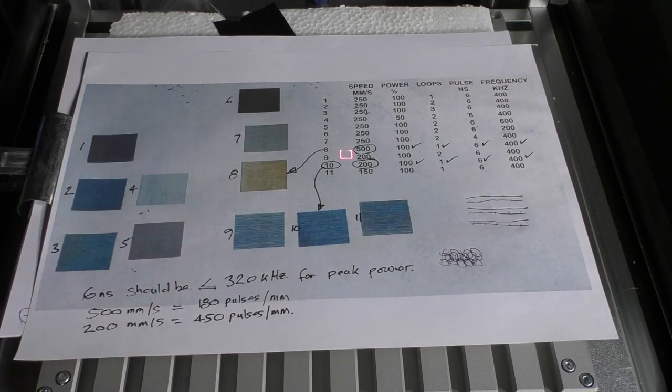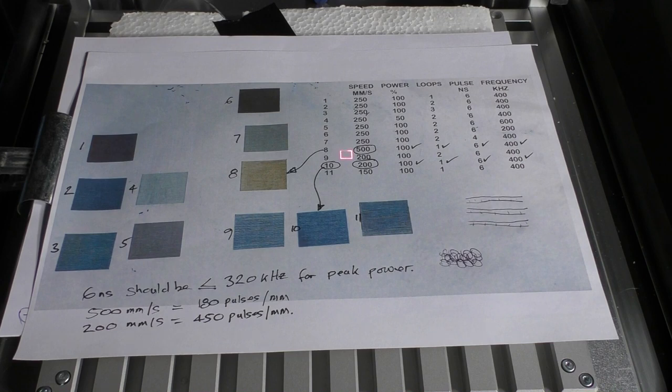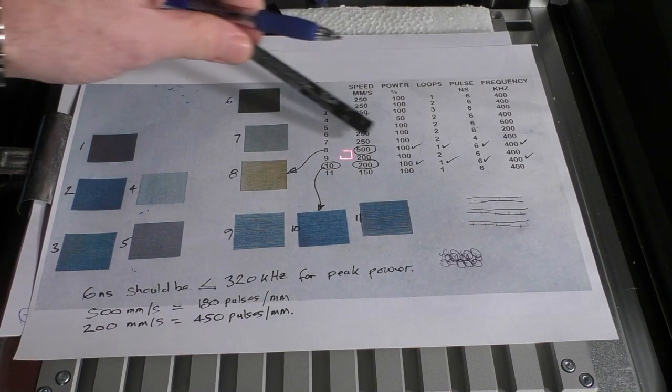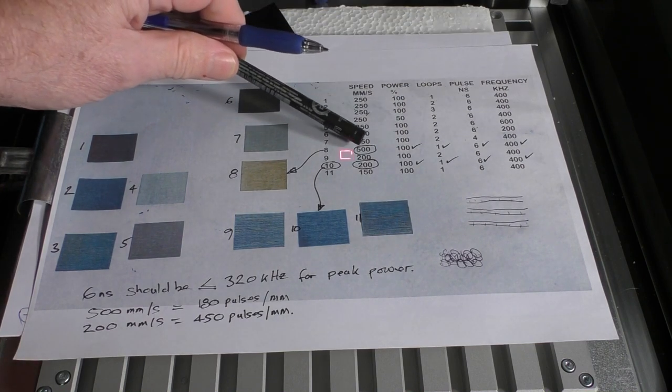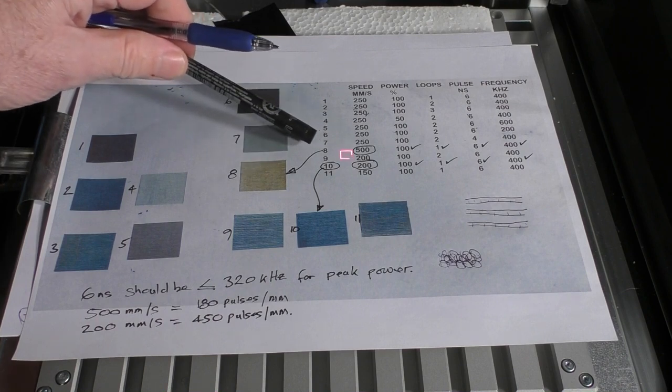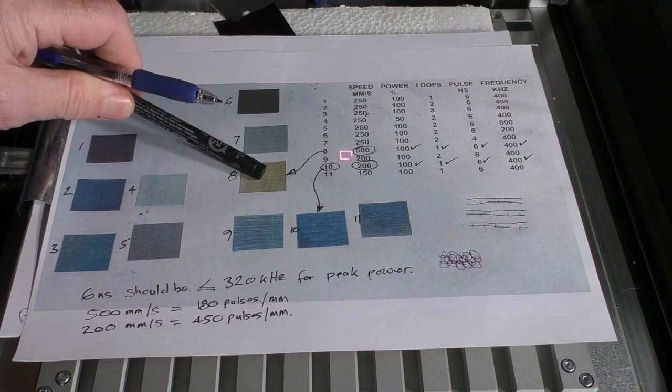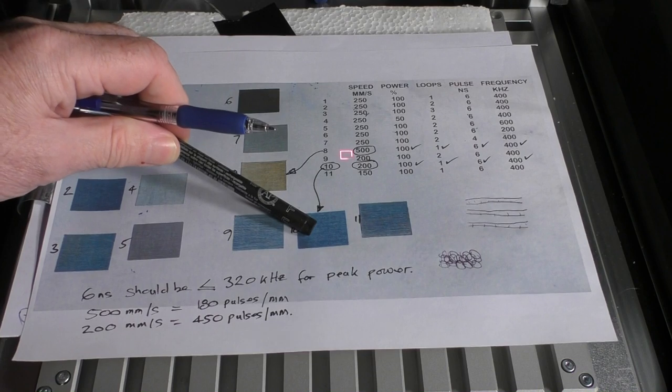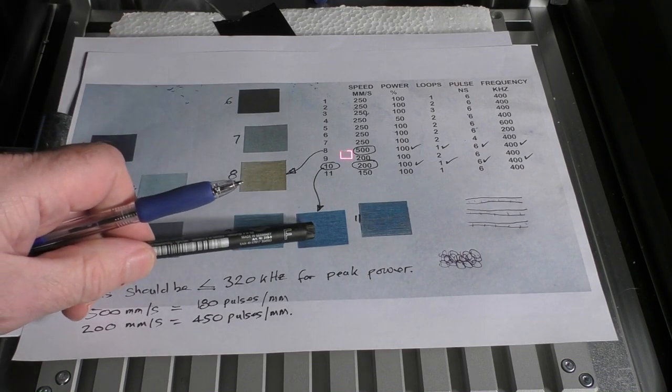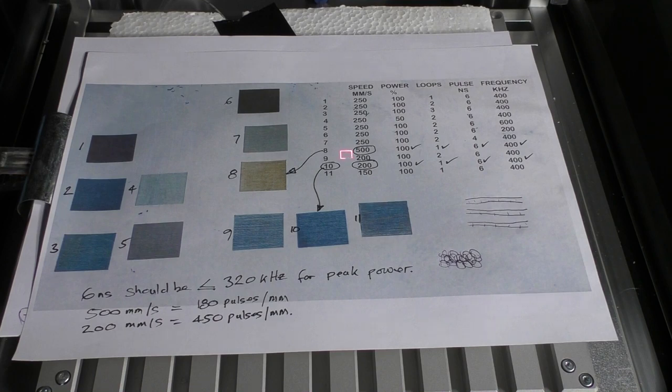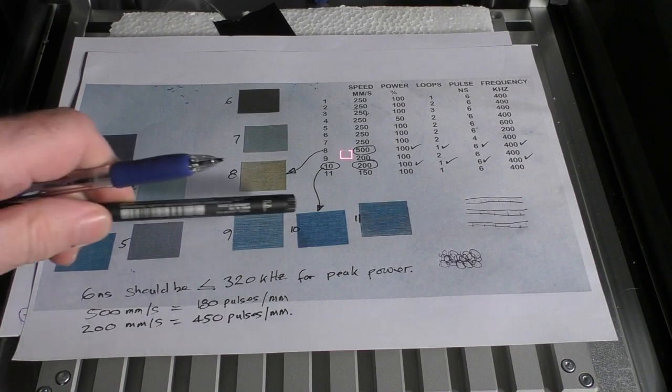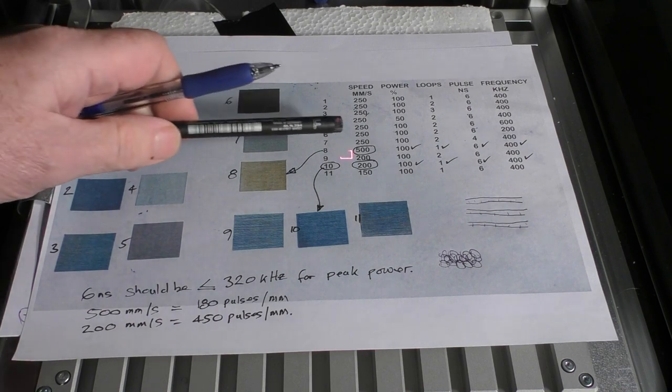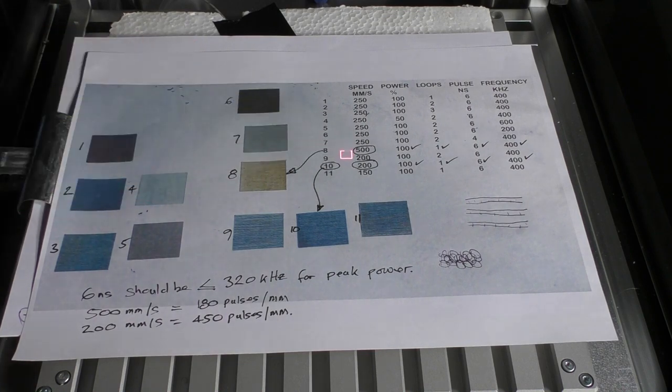I mean the gold and the blue. After a lot of time spent hunting for some magic numbers, everything was common here except the speed. At a speed of 500 I got gold and a speed of 200 I got blue-ish. This is a gross exaggeration of reality but it was a bluey hue that I got. So it seemed as though speed was the magic number.